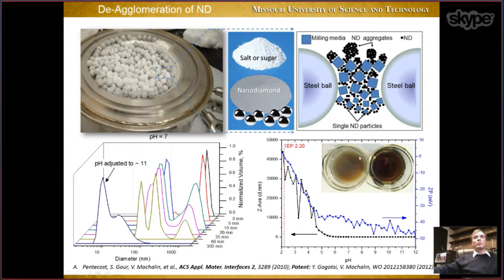And this is how they look before milling. So this is what I get when I disperse nanodiamond after purification and air oxidation. But without milling, when I try to disperse it in water, you see the liquid is cloudy. So the size of agglomerates is in the micrometer range. And when I do milling and disperse it in water, this is what I get. It's a clear solution. It still has a dark brown color.